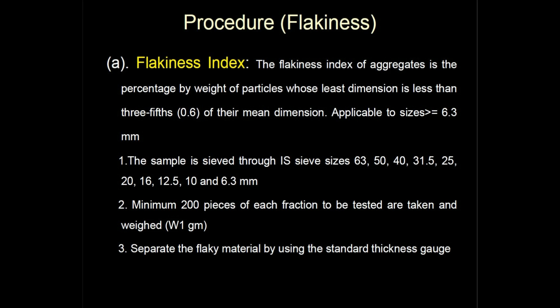The first step of the practical is to take a sample for sieve analysis. The sample is sieved through sieves of sizes 63 mm, 50 mm, 40 mm, 31.5 mm, 25 mm, down to 6.3 mm. After sieving the sample, we proceed to the next step.